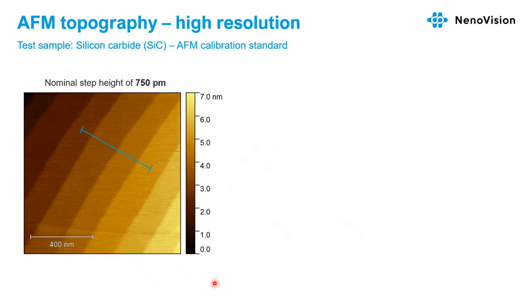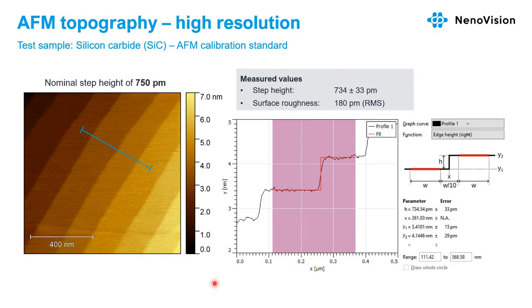I have an example of high-resolution measurement. It's a silicon carbide sample. It's an AFM calibration standard. And so this sample has a nominal step height of less than a nanometer, and we were able to measure this Z step. And so we are at the limit. So we measured the step height of these terraces.